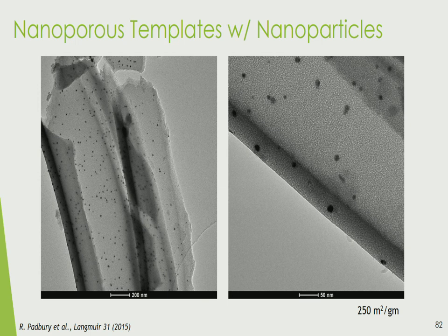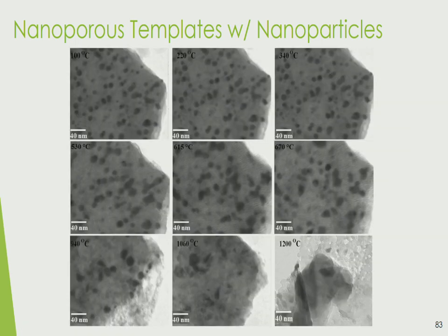We can dump nanoparticles in here if we want to, and the nanoparticles actually diffuse into that hybrid material. And it actually forms very nice cages around them. So this is the burned out polymer again with the nanoparticles, and the metal oxide framework that goes around it actually produces a kind of nano cage that we place around the nanoparticles, and it prevents the nanoparticles from migrating together and coalescing as we anneal those nanoparticles.